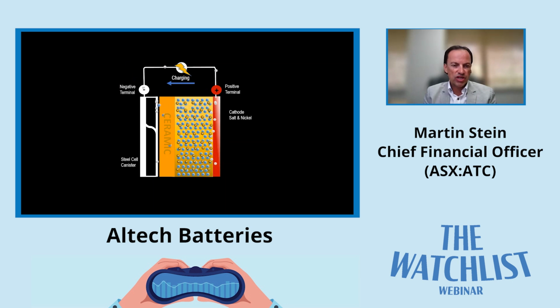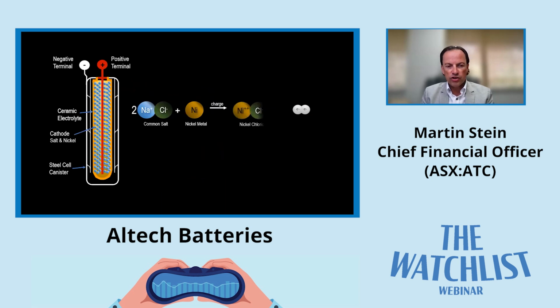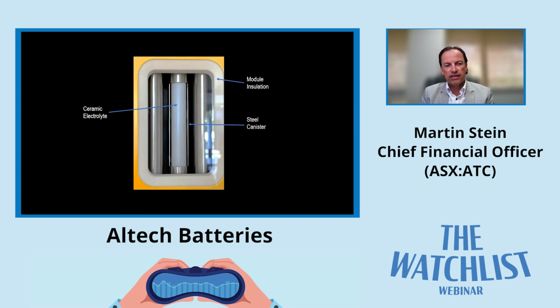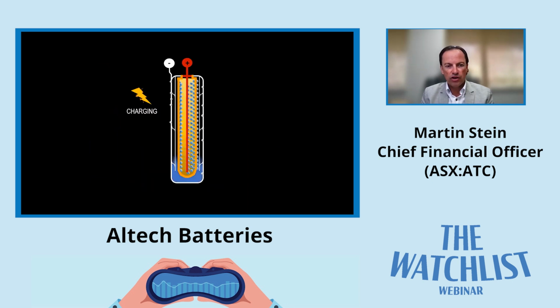There's a little gap between the ceramic electrolyte and the stainless steel canister. And what happens when we charge the battery is that the sodium leaves the chloride ions, the chloride ions stick to the nickel ions, and the sodium ions migrate through the ceramic electrolyte and form a self-forming sodium anode between the stainless steel canister and the ceramic electrolyte. And it is because of this chemistry that the battery doesn't require the lithium, the copper, the cobalt, the graphite, or the manganese. It uses sodium chloride, the table salt, and nickel powder.